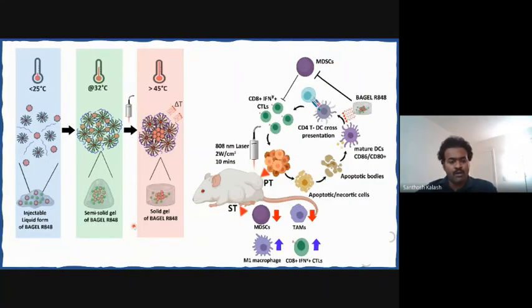So overall, my final conclusion is that we have developed a hydrogel in an injectable form. You can use it directly as an injection, but you have to maintain the temperature at 4 degrees. After injecting, at body temperature they form a semi-solid hydrogel, and due to the laser, they form a solid hydrogel. This helps both in drug retention and in improving the photothermal heat conversion.